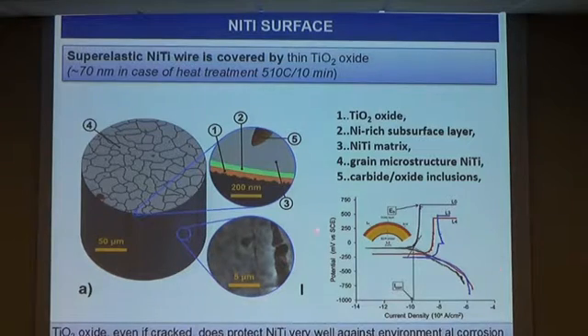To test the corrosion fight against the environment, one can perform a potentiodynamic test, and this is on the oxide which is just in pristine condition, but if you bend the wire, you break the oxide, you get a little bit different behavior, but it's not a disaster. It still performs quite well. And we put the wire on the spring and put it for half a year into very aggressive fluids, and even after that the strength didn't change. So actually, if it's static, the oxide works quite well and can protect the wire.